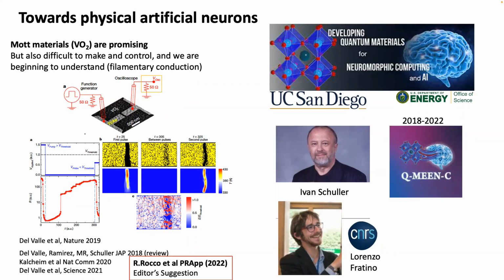VO2 has a first-order metal-insulator transition at 60 degrees centigrade, so it's very convenient for us. We amuse ourselves doing these simulations, and we have very strong interactions with the experimental group, trying to understand and make sense of very unusual behaviors that we observe, pushing these Mott insulators out of equilibrium.